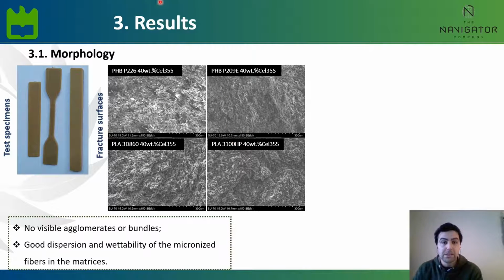Now moving on to the results and starting with morphology, we know that many of the properties in the composites depend on the ability to transfer energy from the matrix to the fibers, which in its turn depends on the dispersion of the fibers and on the interface between the matrix and the reinforcements. On the plus side, when looking at the test specimens, or even at fracture surfaces of the composites, there are not any visible agglomerates or bundles of cellulose, either in any of the composites with different matrices, composites with different micronized fibers having different aspect ratios, or even composites with different fiber loads. And this is a clear indication of the good dispersion and wettability of the micronized fibers in the different PLA and PHB matrices.